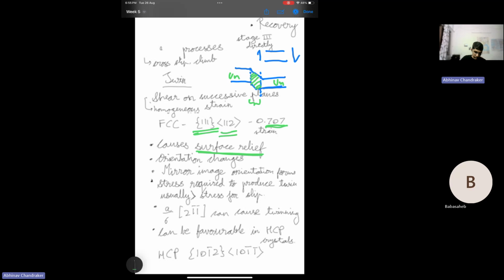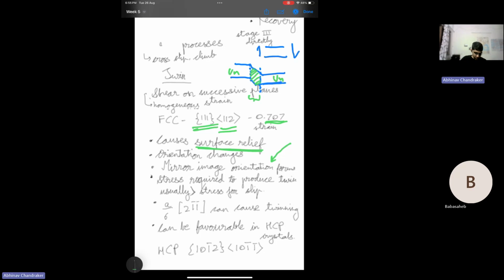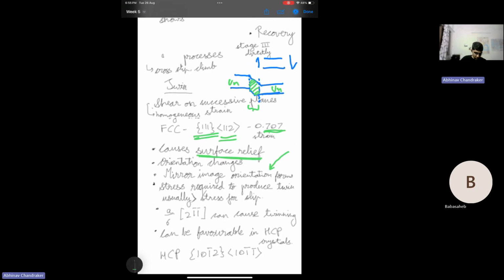This is a characteristic of twins which helps in identifying twins in materials, especially when you are doing EBSD or TEM, transmission electron microscopy, to be able to know the microstructure and orientation of the different grains and other defects like twins. So the orientation is a mirror image.